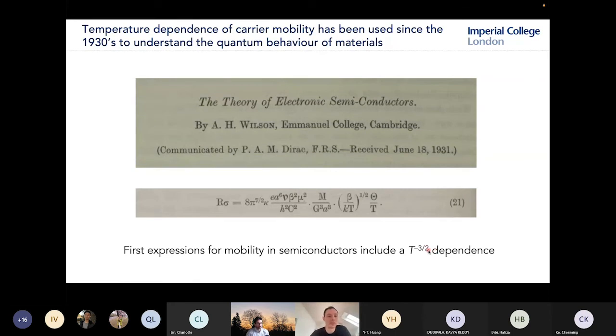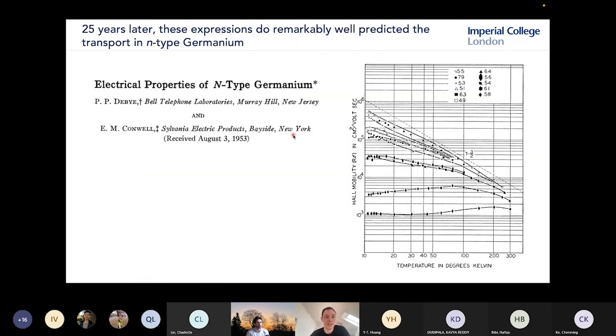What was nice was that about 25 years later, his calculations went on to agree very well with transport properties measured in N-type germanium. These were measurements done at Bell Labs, and here it's showing the experimental mobility, and this is the ideal T⁻³ᐟ², and you can see there's some really nice agreement here.